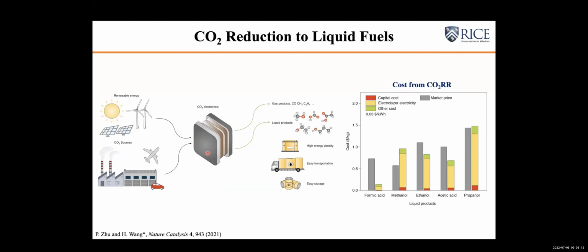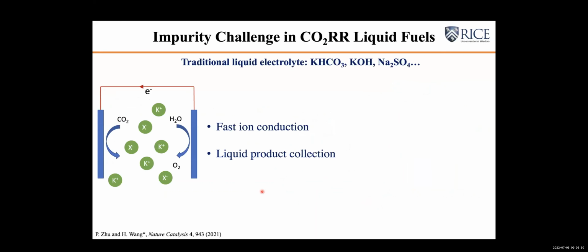Because we know that in gas products, if you have excessive CO2, you have to do a downstream separation process to separate that CO2 and feed it back to your reactor again. But for liquid products, there is no need for that part. And also a lot of these techno-economic analyses suggest a very competitive cost of liquid fuels coming from CO2 reduction compared with the existing technology. However, I want to say here that this type of techno-economic analysis overlooked a very, very important factor that people recently noticed, which is the impurity issue, especially for liquid products.